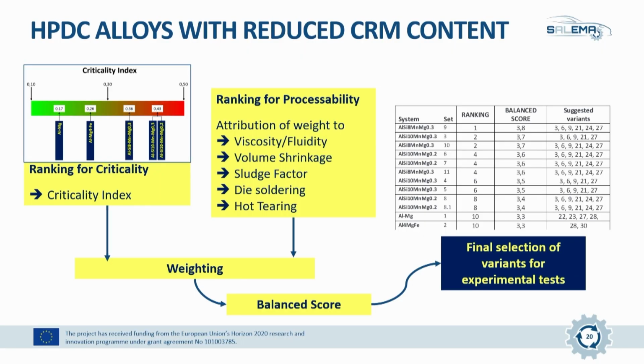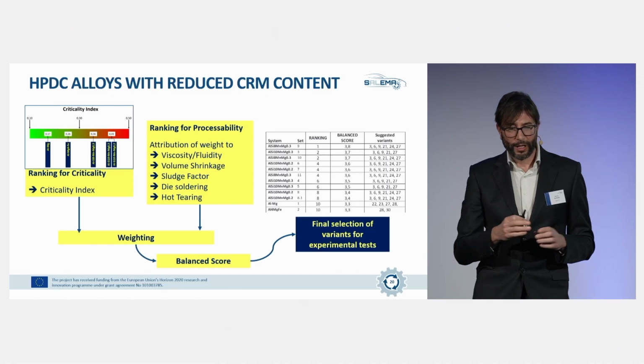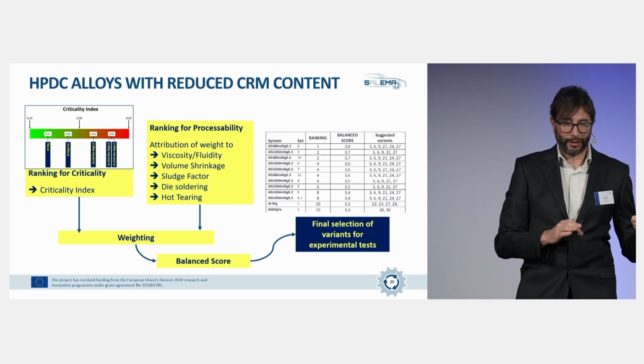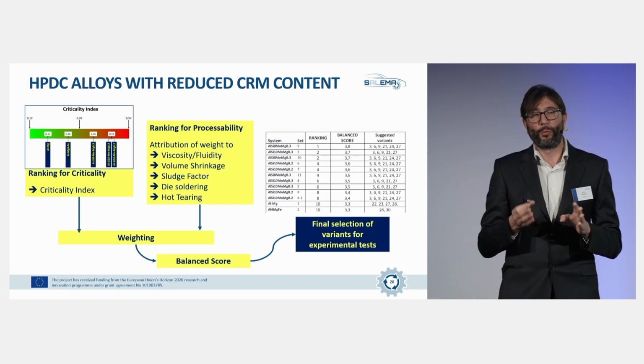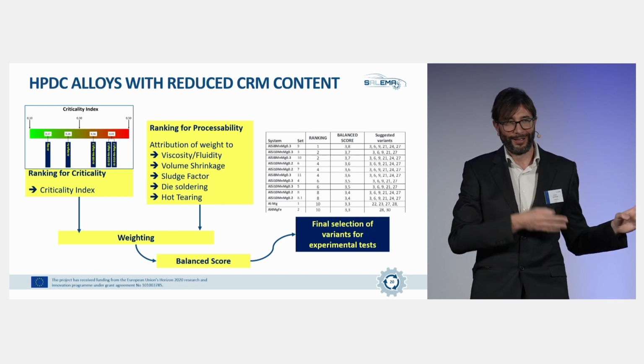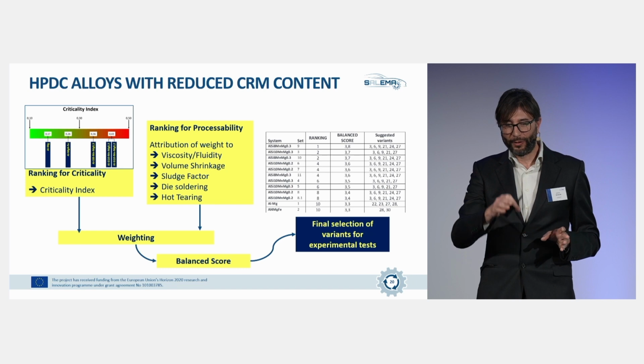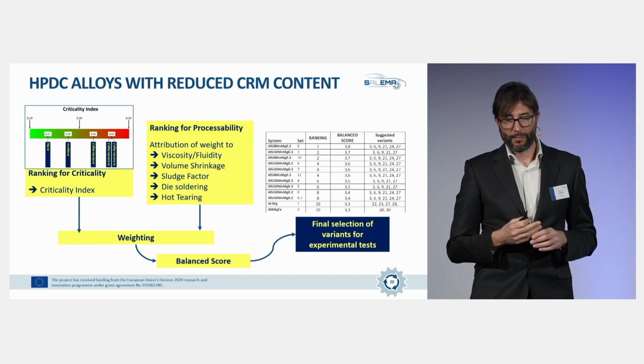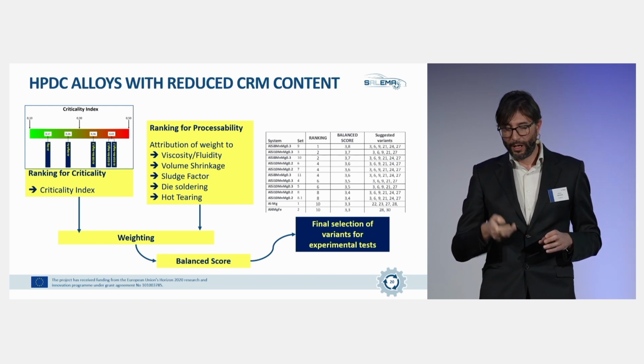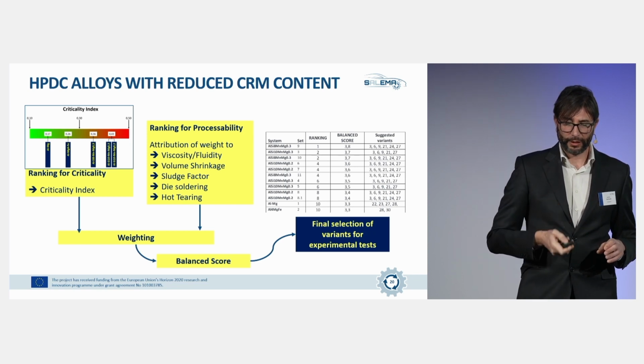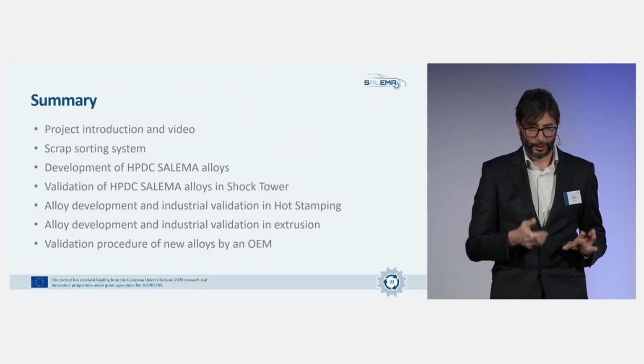So, with that, we had a proposal of over 150 alloy variants, with different compositions. We evaluate the criticality index, and also, with the model, the castability of the alloy by measuring the viscosity predicted by Thermo-Calc and other factors. And then we weighted 1/3 for the criticality index and 2/3 for the processability. It's more important to be able to produce the component than the criticality of the alloy. And with the weighting, we rank the alloys from the best scoring to the least. And from this scoring, the 7 best alloy variants were selected. Well, one back, sorry.